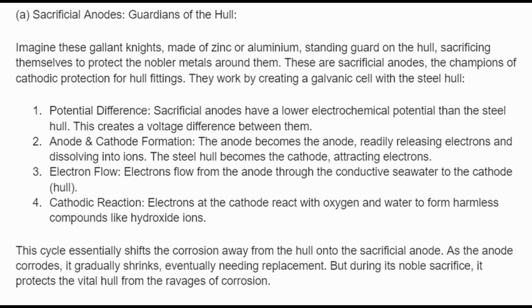4. Cathodic reaction. Electrons at the cathode react with oxygen and water to form harmless compounds like hydroxide ions. This cycle essentially shifts the corrosion away from the hull onto the sacrificial anode. As the anode corrodes, it gradually shrinks, eventually needing replacement. But during its sacrifice, it protects the hull from the ravages of corrosion.